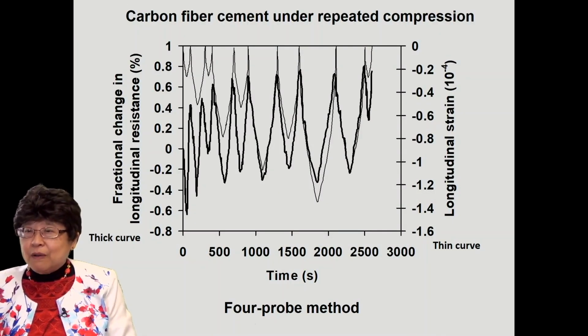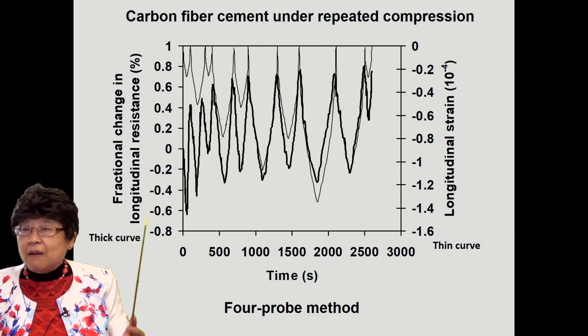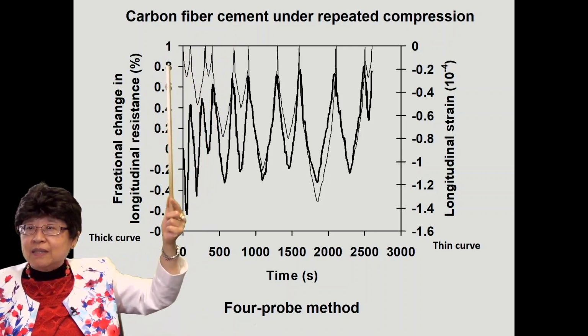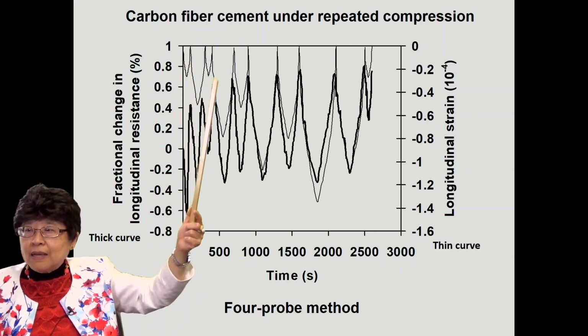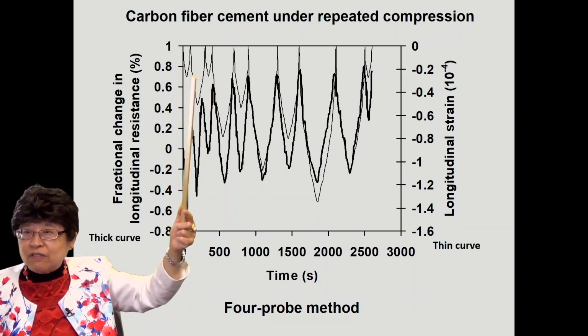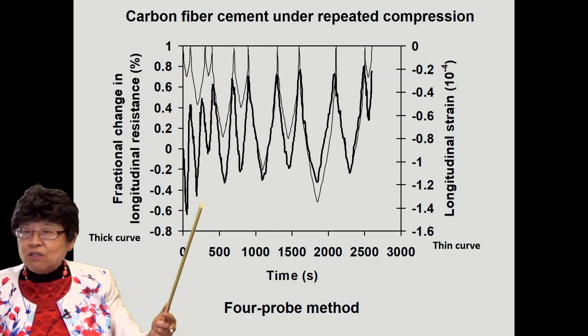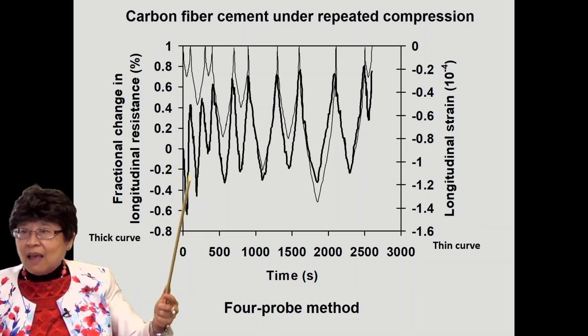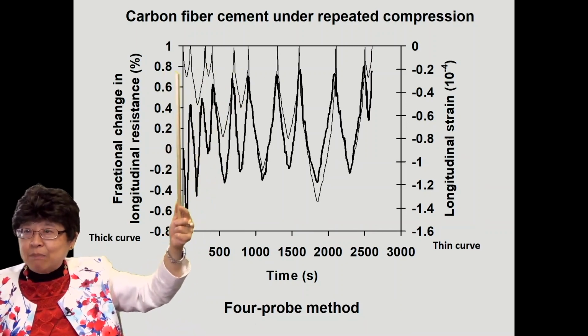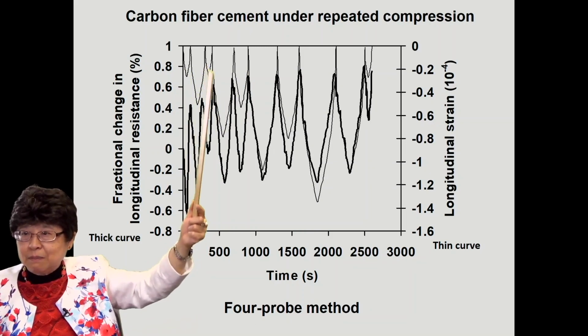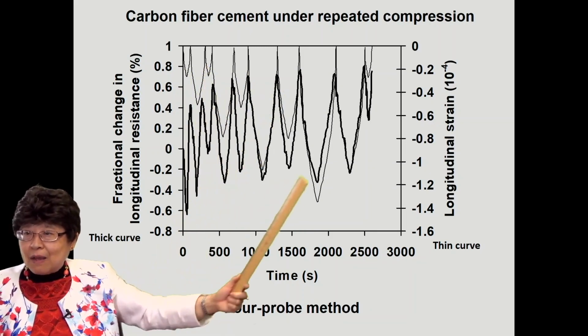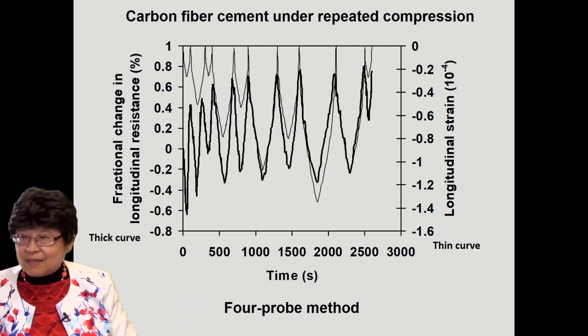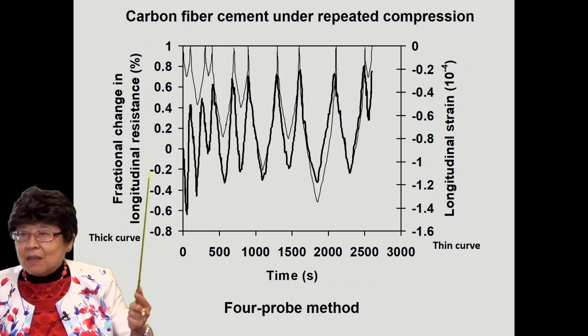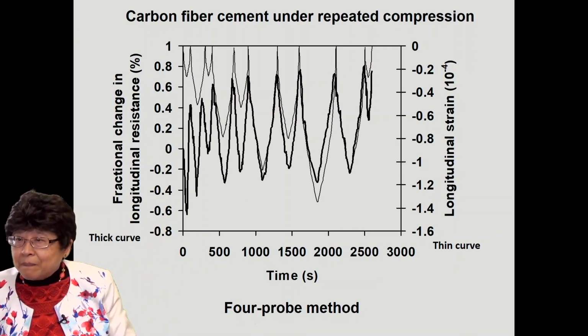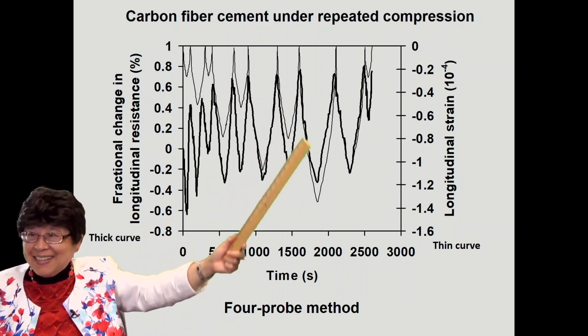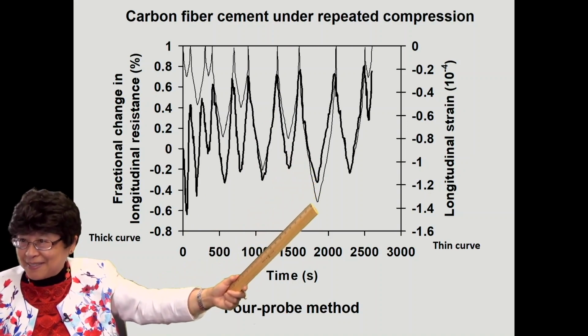This is an example of the resistance change in the case of carbon fiber cement under repeated compression. The thin curve is the strain along the direction of compression, and the thick curve is the fractional change in resistance in the same direction. Note that I have arbitrarily applied a progression of strain amplitudes, each a little bigger, and I follow that in terms of the resistance. And you can see the resistance decreases whenever one compresses.